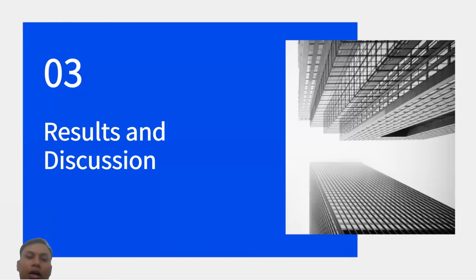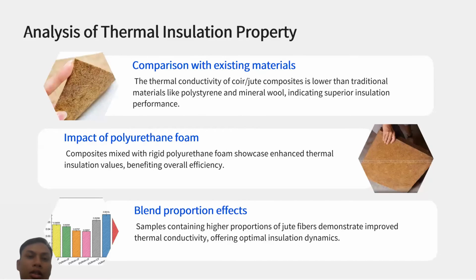3. Results and discussion. Analysis of thermal insulation property. We have to compare the composite with existing materials. The thermal conductivity of coir or jute composites is lower than traditional materials like polystyrene and mineral wool, indicating superior insulation performance. Impact of polyurethane foam. Composites mixed with rigid polyurethane foam showcase enhanced thermal insulation values, benefiting overall efficiency. Blend proportion effect. Samples containing higher proportions of jute fibers demonstrate improved thermal conductivity, offering optimal insulation dynamic.